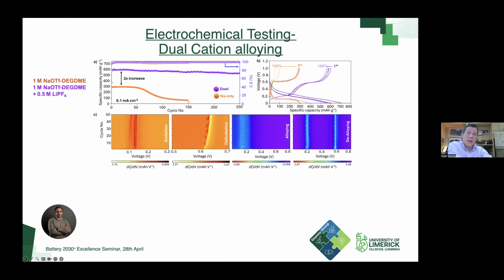Looking at the electrochemical fingerprint of this, this is your characteristic germanium alloying with sodium. What we're seeing is that the desodiation is a single feature which shifts over time. In our dual ion system, it's much broader. You'll see this in the voltage profile, that you have much more activity over a wider potential range during alloying. What this hints at, and we'll show it in the next slide, is that you have more interaction between the two ions as you go along. And then we have two main features in the de-alloying portion as well.